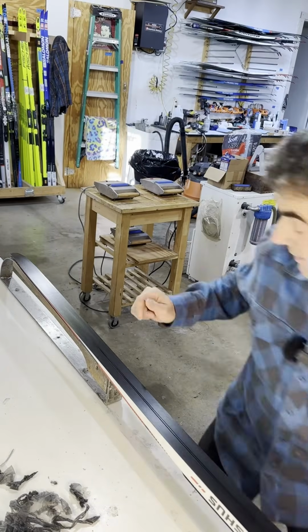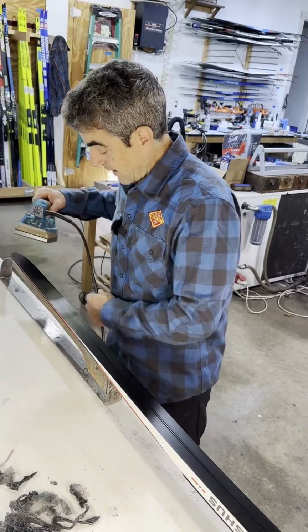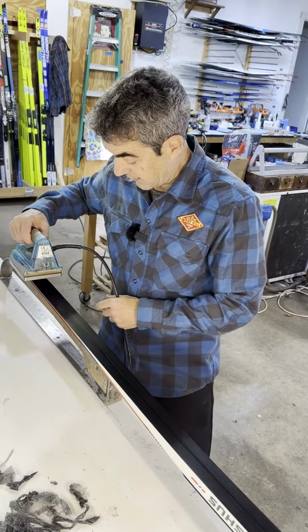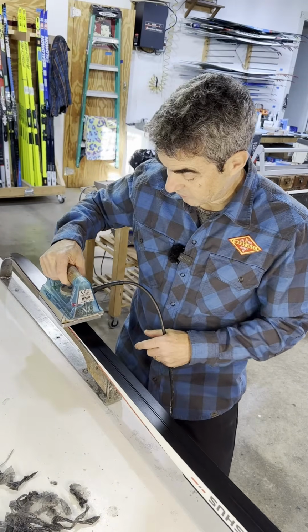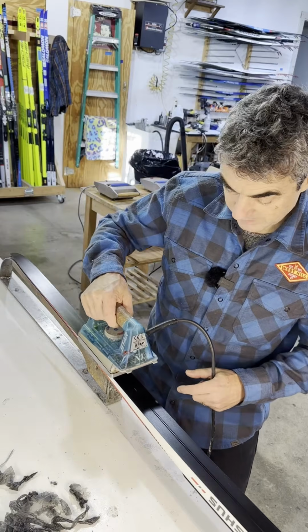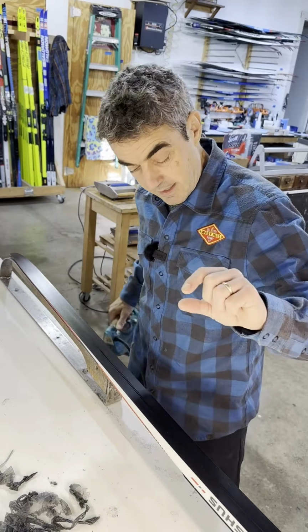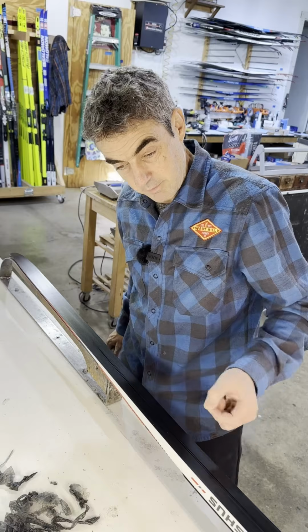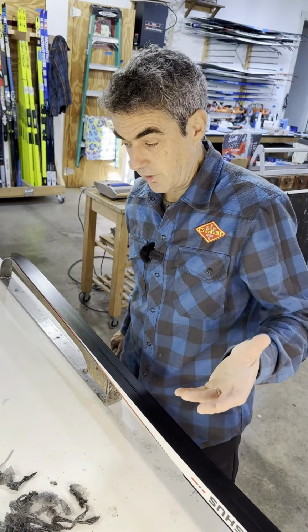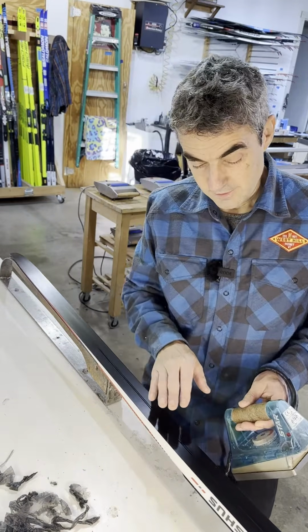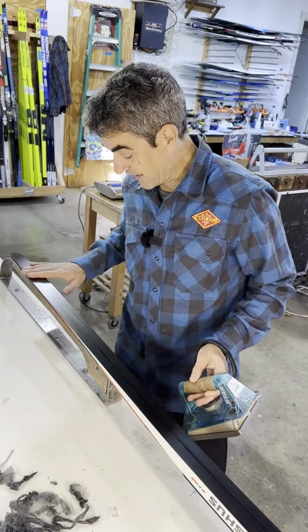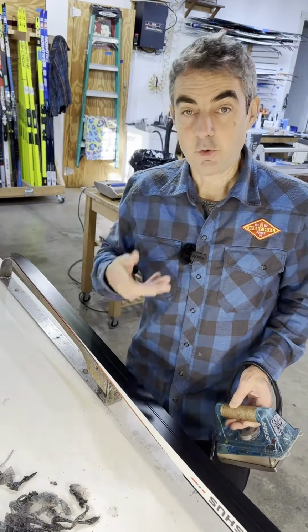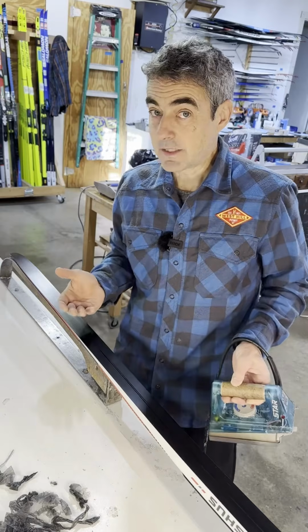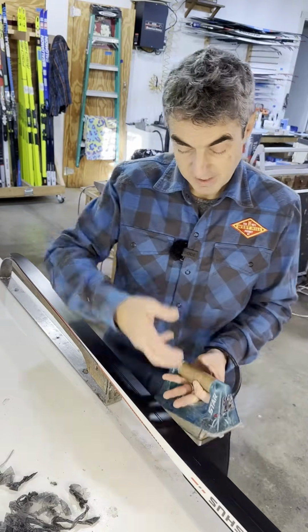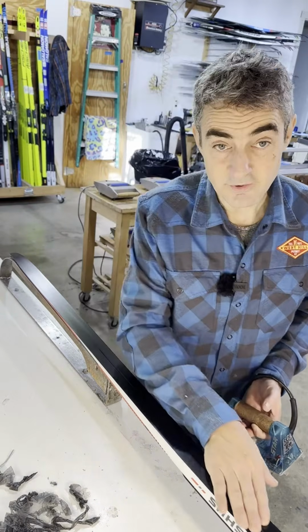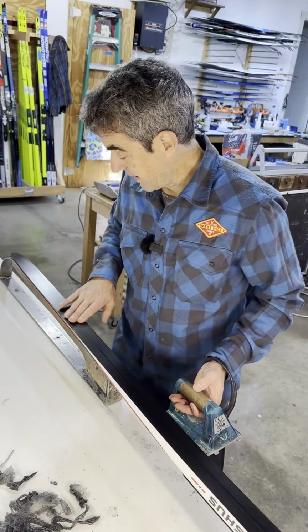Now let's imagine this. If we take an iron and wax and we iron the ski, and it's starting at room temperature, and we're going one slow pass, we really don't have to hurry because we've got a very steep thermal gradient in the base. That millimeter of base material is 20 degrees Celsius, room temperature. When we return and we come back for a second pass, that heat that we've put into the base, well, it's not that much, it's just one pass, has spread out. And now the base is a higher temperature.